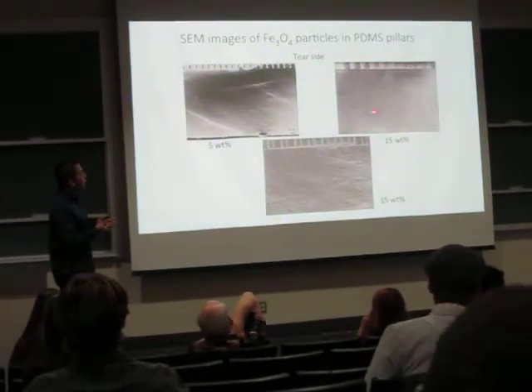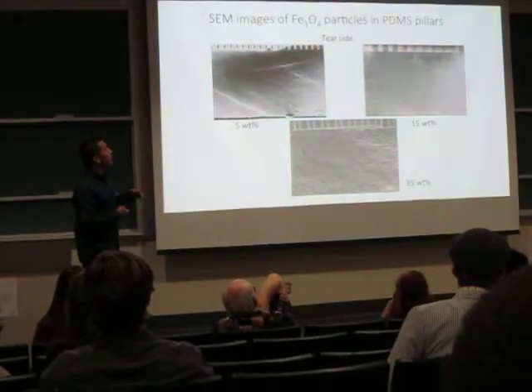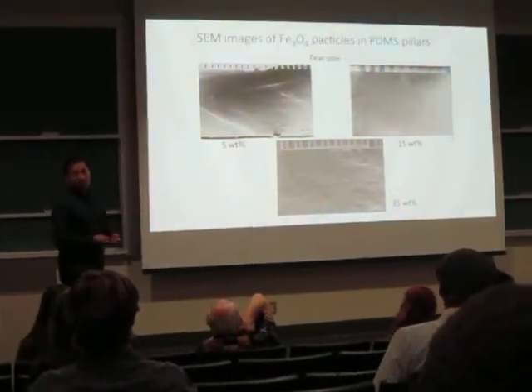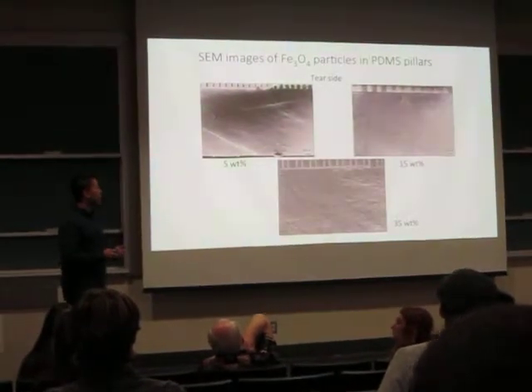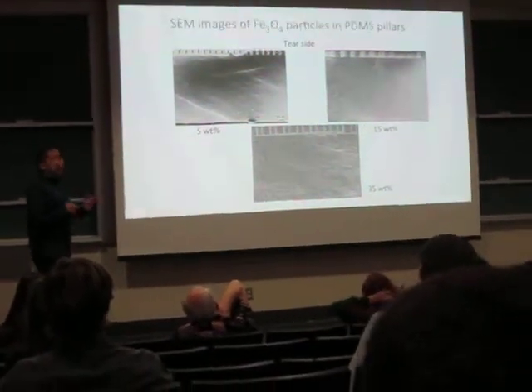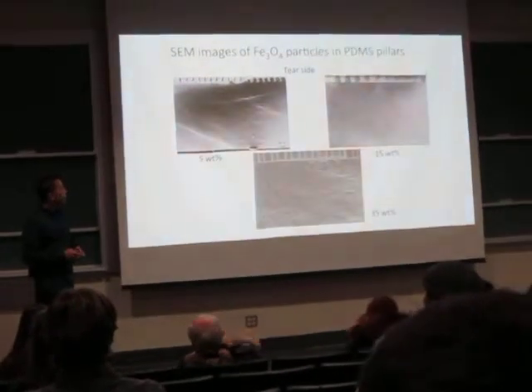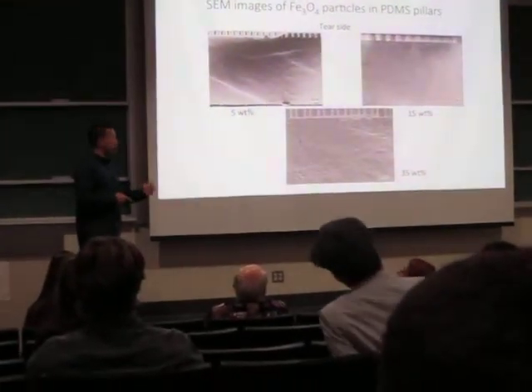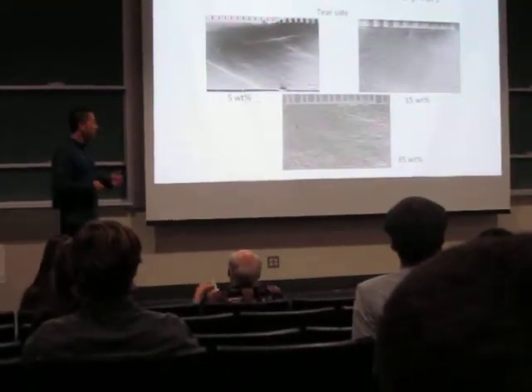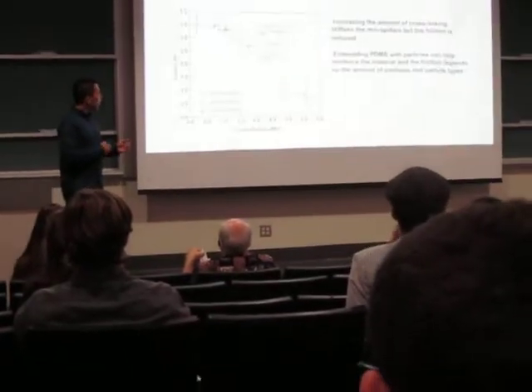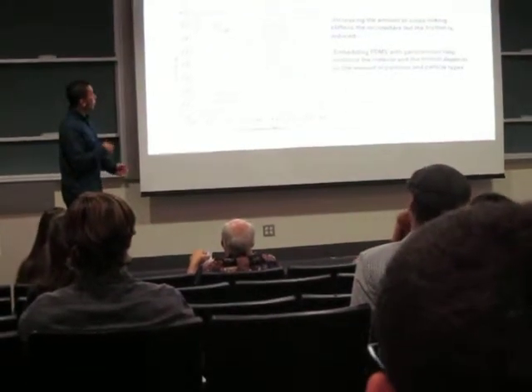And as we're adding 15 weight percent, as we're adding more black iron oxide particles, we make the material itself stronger, which reduces the frictional force. But when we're adding a lot of particles, the frictional force goes back up.